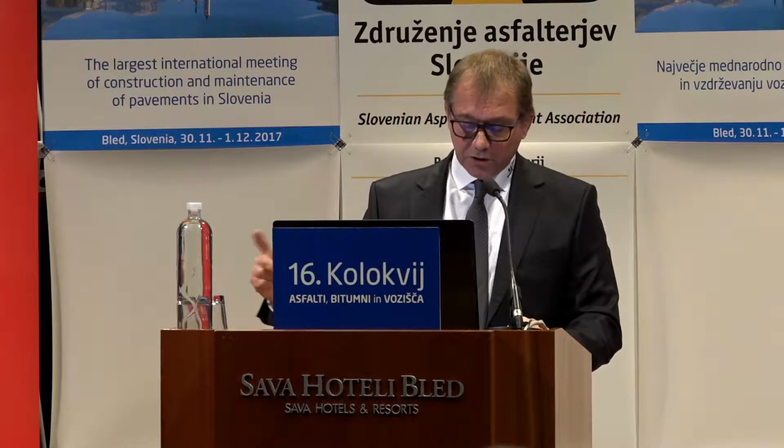Today I'm talking about, of course, our S&P asphalt reinforcement grids made completely of glass and/or carbon. That's the difference, glass and/or carbon, which have an excellent shear bond behavior, prevent crack reflections, crack formations, and if they are applied on the right level, they also could help to slow down the rutting process. Mostly applied between wearing and binder courses. The higher, the better.